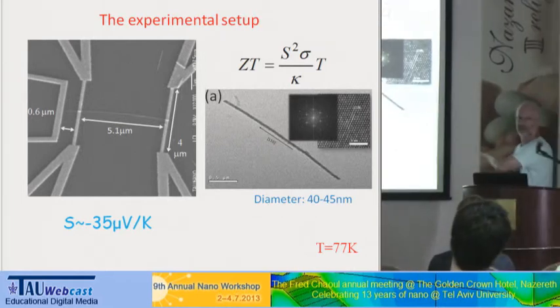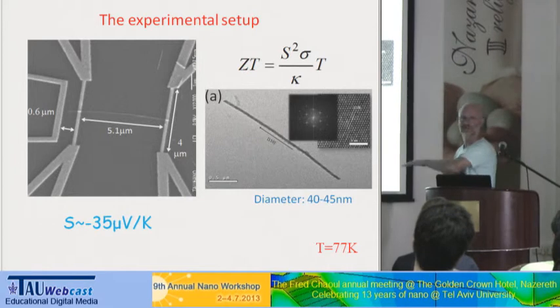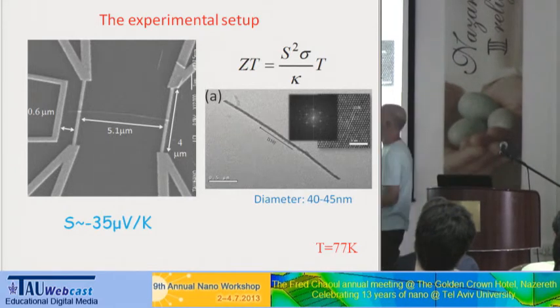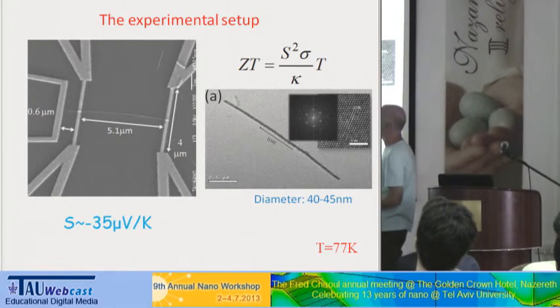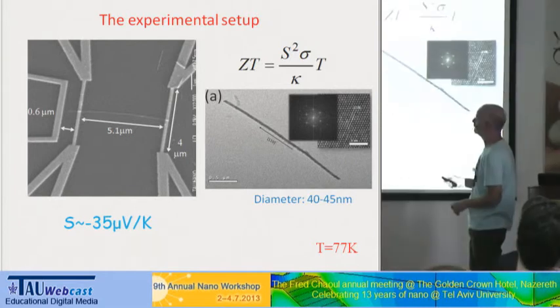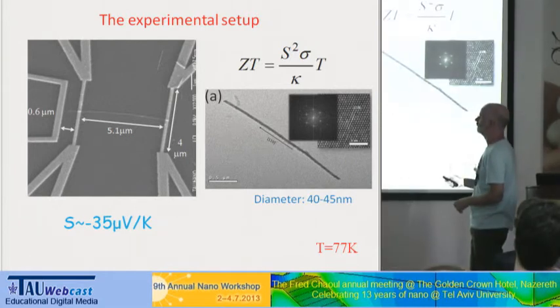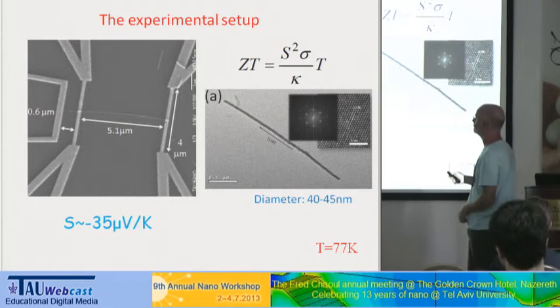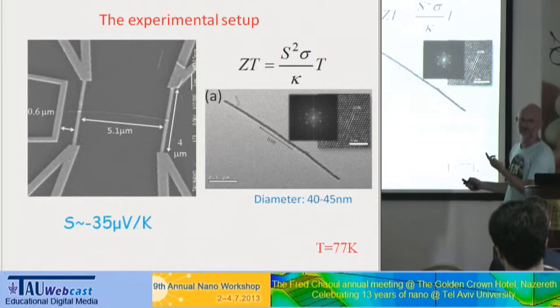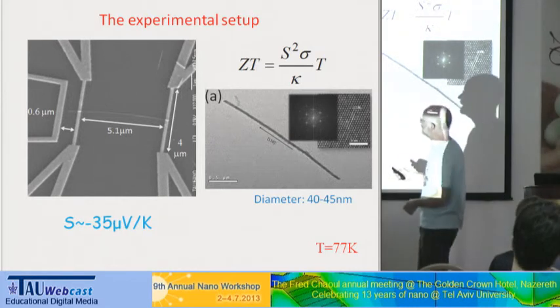Everything here is on an insulator, so this is on silicon oxide underneath. And then we have a heater. So we pass high current through the heater, and everything here becomes hot, and then you have a temperature gradient across the wire. So if you measure the voltage between these 2 points, you have delta V, which is essential in order to characterize the Seebeck coefficient. The next thing that you need to know is what is delta T between the 2 points, and this is why you have this structure here.